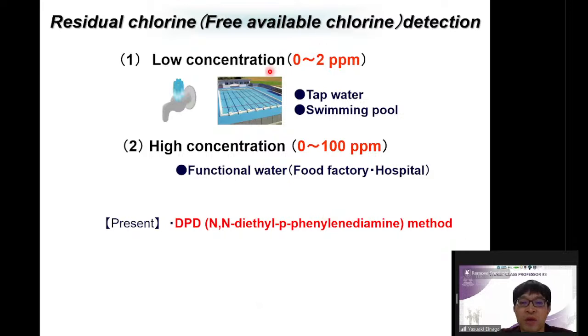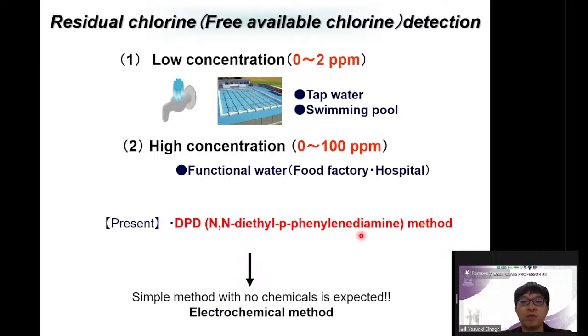The purpose of this free chlorine detection is, for example, to detect free chlorine in tap water or swimming pools. And not only that, but some food factories or hospitals also need detection in this concentration region. So far, the DPD method is normal for detecting chlorine. When we want to measure chlorine, this DPD reagent should be put in the sample, then it shows color and we detect the absorption spectra. This is a bit troublesome because we need these chemicals, but without chemicals, there is a very simple method: the electrochemical method. So this is our purpose.